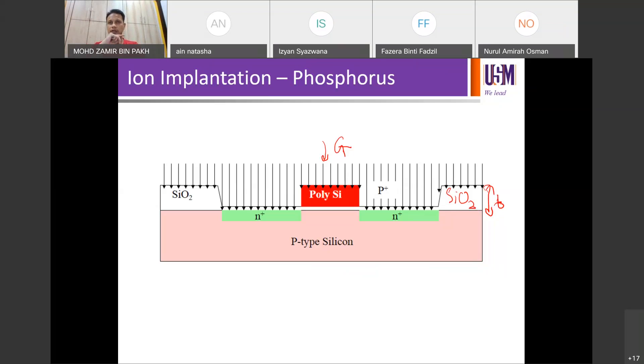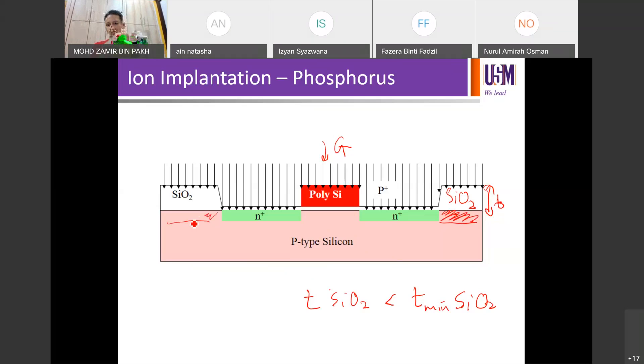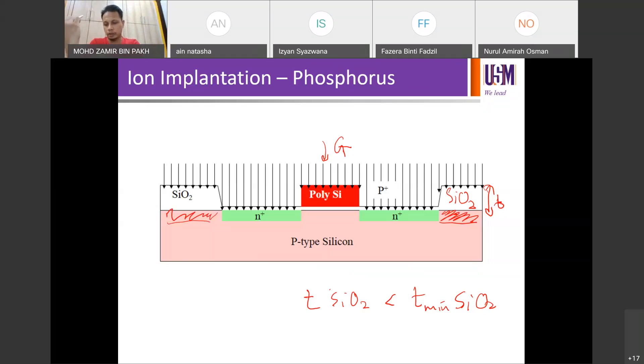If your SiO2 thickness is not enough, the areas under the mask will also be doped — not only the open areas. That's the impact of insufficient silicon dioxide mask thickness. After thermal oxidation, you need to verify the SiO2 thickness grown during the process so that it effectively works as a mask during diffusion or ion implantation.